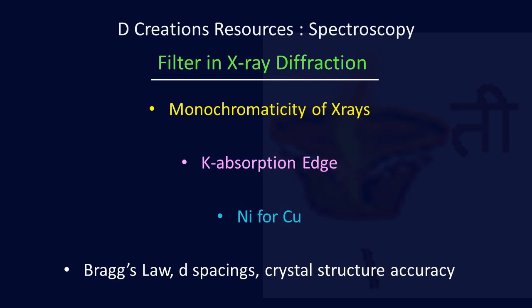Now the material of the filter is chosen such that the K absorption edge lies between the K alpha and K beta wavelengths of the target material. Let's take an example. Copper is one of the most commonly used target materials, and the filter used here has atomic number just one less than copper. So copper is 29 and nickel is 28, and nickel is the filter used. Why is it used? Because if you look at the copper K alpha wavelengths, copper K alpha is around 1.542 angstrom, while copper K beta is around 1.3922 angstrom. Now, you have to look at the K absorption edge of nickel, which is around 1.488 angstrom.